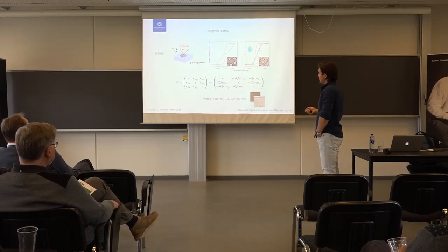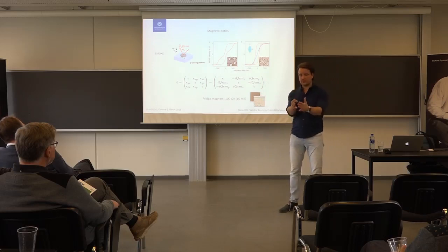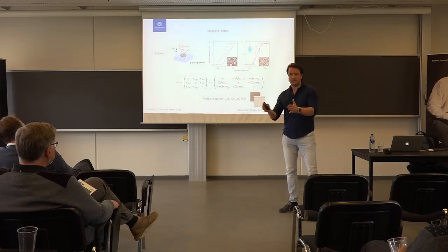The thing is that, of course, you could make nanostructures out of these ferromagnets, that's what we're doing. And when you measure something like that, you can ramp your magnetic field. How do you measure how the material is magnetized? You measure the response at each applied magnetic field and see when it saturates, so it's fully magnetized.